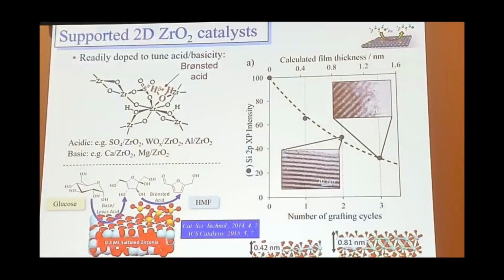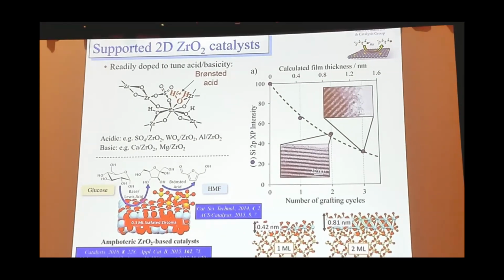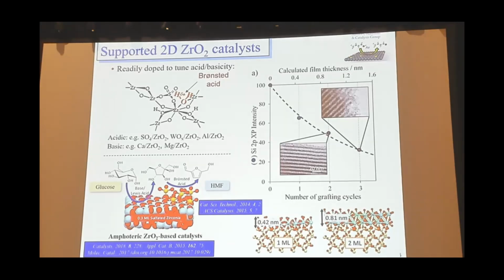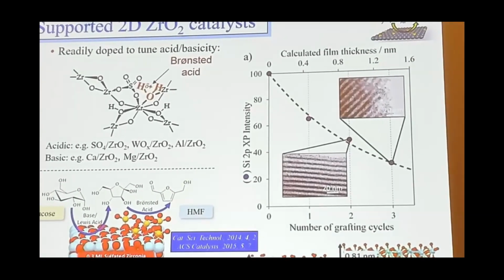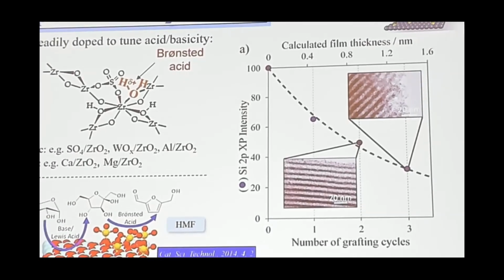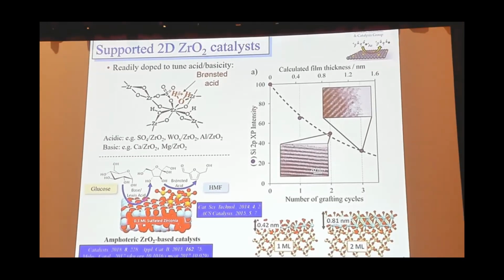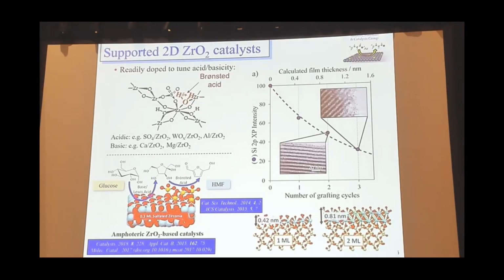We've looked at the same type of chemistry on the two-dimensional films grown on SBA-15. This just shows you how well behaved the deposition is. This is actually the liquid phase grafting of zirconium propoxide onto SBA-15. If you look at the XPS, you can calculate what the attenuation of your underlying silicon signal would be as you grow 1, 2, 3 layers of zirconium, and calculate what the thickness of that film would be. So the dotted line is the predicted attenuation of the silicon signal for 1, 2, and 3 layers of zirconia. We can see that the data points lie very well on that line, confirming that you actually have a nice layer by layer growth.